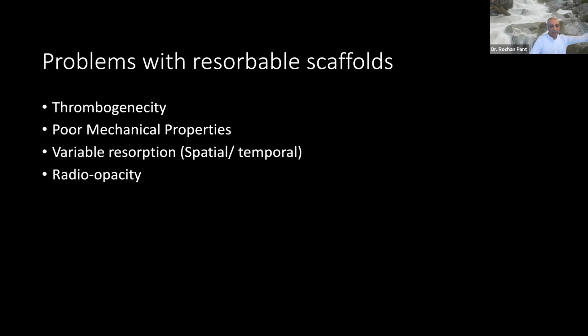So what are the problems with these resorbable scaffolds? They're not without problems. So late thrombosis has been a problem. So most of the time with most of these scaffolds, the instructions for use ask us to continue dual antiplatelets for longer than with usual stents. Mechanical properties have been questionable as compared to cobalt chromium and platinum chromium stents. Again, the resorption has not been completely predictable, perhaps because of individual differences or manufacturing practices. Radio opacity has consistently been a problem for these stents.